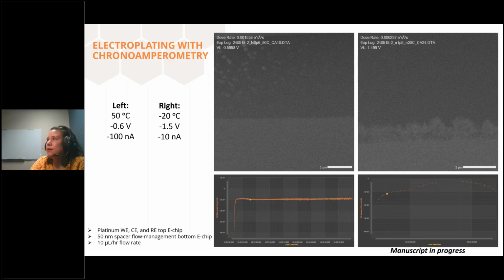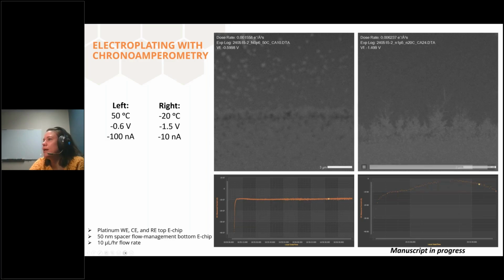So likewise, here on the left, we see at 50 degrees C, we apply a negative 0.6 volt potential, versus on the right, when we're at negative 20 degrees C, we actually apply negative 1.5, which is a lot for a liquid cell. But again, you see some plating occur. We don't have any de-wetting or anything like that. And there's clear morphological differences between the two.